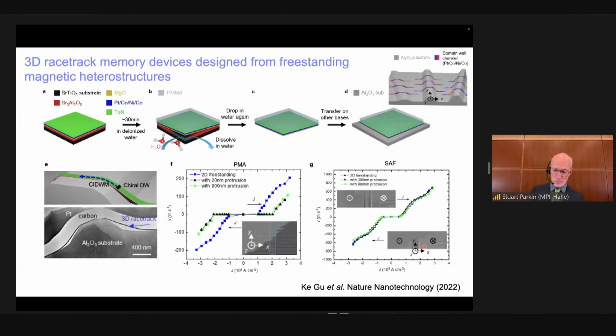So I'm running out of time, but I did want to say, in my institute in Germany, we have several programs to develop 3D racetrack. And I think this is a beautiful example. We've recently published, this is by a student, Kei Gu of mine, in which we use a very elegant technique in which on the substrate, the wafer, we grow first a water-soluble oxide layer. And on top of this oxide layer, we grow our atomically engineered racetrack. Then we dissolve the oxide layer from the edges of our wafer.